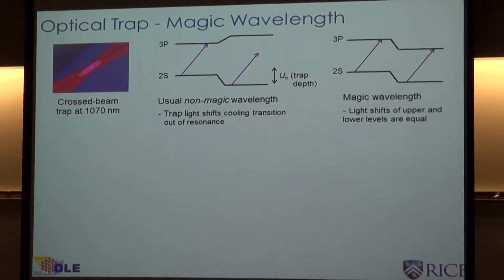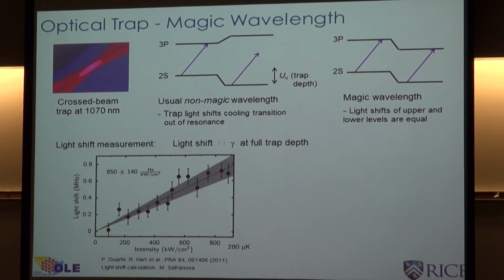But in very special situations, and this is something we found from Charles Clark and Mariana Safronova, there's a magic wavelength in this transition that happens to be at exactly the wavelength of our optical trap, 1.07 microns. So we were very, very fortunate to find this out. The advantage is that you can now do laser cooling inside this optical trap. This is showing that the light shift really is tiny for this spectral line.